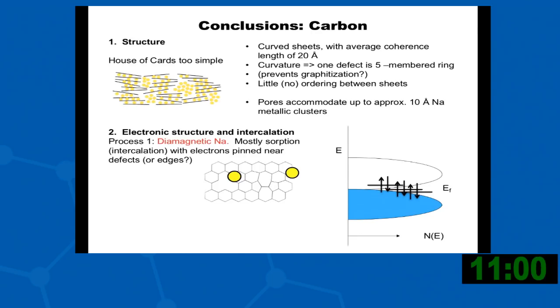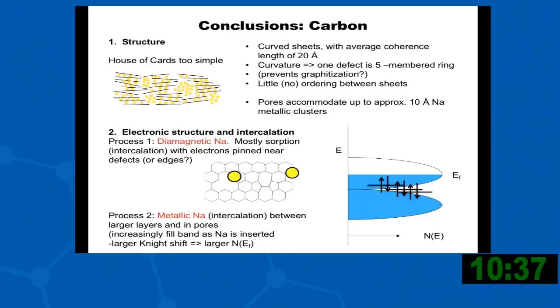So we can put this together. A mechanism with a house of cards that was proposed earlier is too simple. Instead, we have these graphene sheets with coherence lengths of about 20 angstroms. They're curved. And then the first thing that happens when you intercalate sodium is that you get a diamagnetic environment, and that tells you that the electrons must be pinned near these defects. You then start to, as you go down into the sloping region, see metallic sodium, and that's when the electrons are delocalized into the carbon sheets.